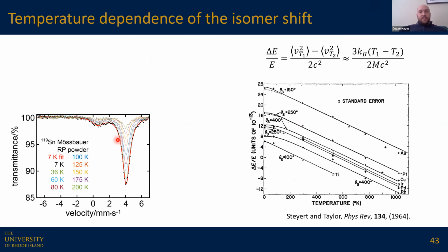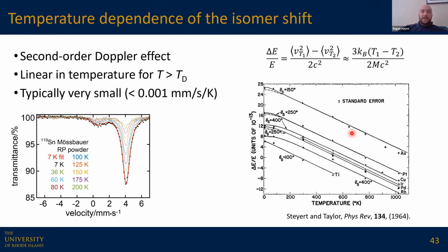There is some change in the spectral shape coming from the second order Doppler effect. And this is just coming from the mean square velocity of the absorbers. And so you get this very small shift that's approximately linear in temperature, on the order of about 0.001 millimeters per second, which is the energy unit for Mossbauer spectroscopy, per Kelvin. So there is some shift, but it's typically very small.